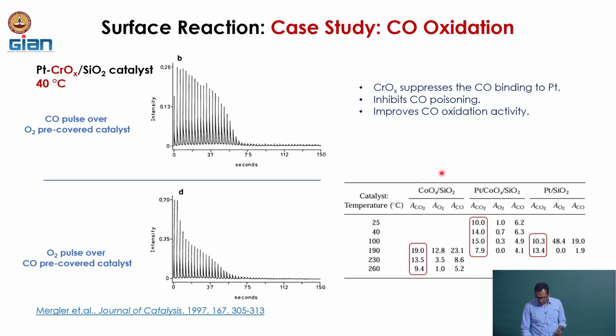And here is just the table that shows you have only the chromium oxide, the mixture of platinum and chromium oxide, and just the platinum, and we can see the area of CO2 is nothing but corresponding to the amount of CO2 that is formed. Okay, just because it is a pulse, they are taking the area, not the rate. Okay. And you can see even at 25 degrees Celsius, we are seeing product which are not observable in this case. Okay.